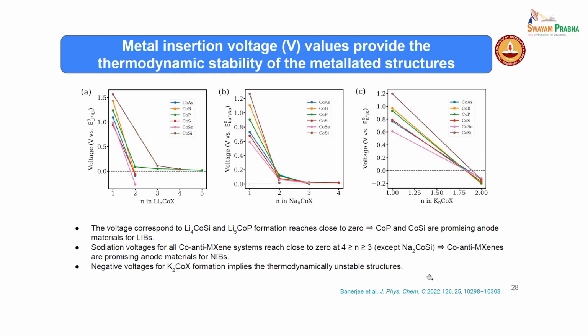So whatever is above 0, only the positive values of the voltage are the ones that I would be considering as proper. And you can see here the number of lithium atoms per formula unit I can add. So if I am considering COX, here cobalt, whatever anti-MXene non-metal atom I am considering, I can go up to 5 for the case of phosphorus, whereas for sodium it is going up to 4 at maximum, whereas for potassium I cannot go even for 2. So although potassium has a good, I mean low, migration energy barrier, because of its strong adsorption energy, it couldn't load more atoms.